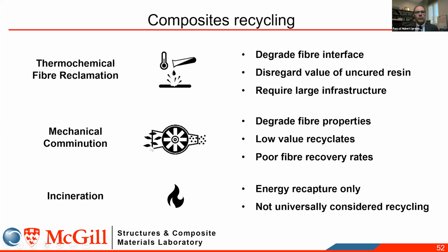Then the approach of just shredding the composite through mechanical comminution will obviously degrade the fibrous properties. You get some kind of filler more than a composite that can be recycled, and you cannot recover a lot of fibers through that process. And finally, the other approach is to say, well, I'm just going to burn the composite and capture the energy. Well, this is one approach, but it's not considered recycling.